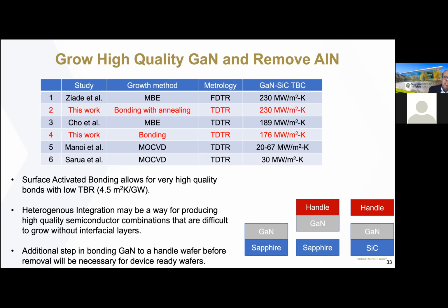What this also points to is that this plasma activated bonding, which we've actually tried with other materials, which I won't have a lot of time to go into, can be used to integrate, mix and match other semiconductors with high thermal conductivity substrates. So it's opening up this toolbox to begin using manufacturing techniques to begin integrating thermally dissipating substrates or heat spreading substrates with these materials that are actually producing a lot of heat from joule heating when the devices are operating.